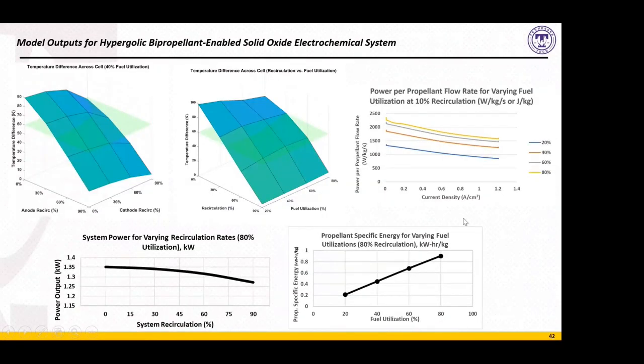Overall system behavior is highly dependent on the recirculation rates, both for the anode and for the cathode. We can also reduce the temperature difference across the cell through fuel utilization, but as we see here, it's less sensitive to fuel utilization changes than it is to recirculation of the exhaust. At different fuel utilizations, we back out a power per propellant flow rate, basically watts per kilogram per second or joules per kilogram from our propellant.